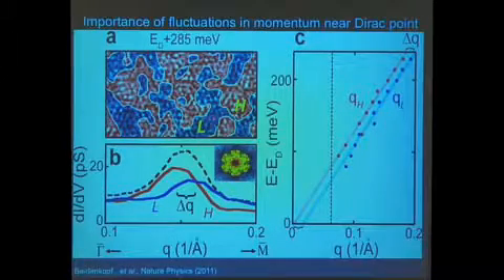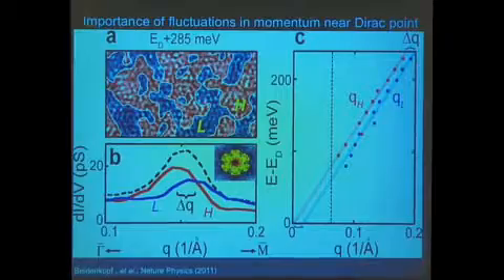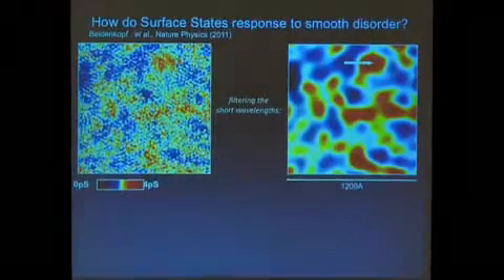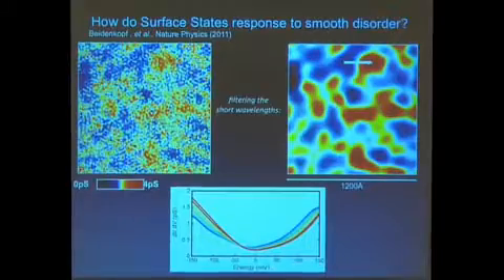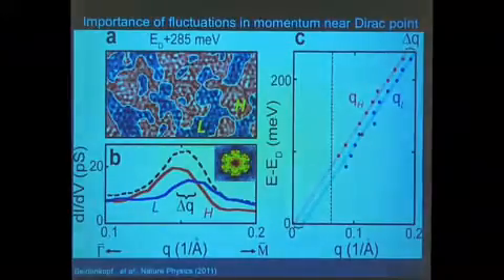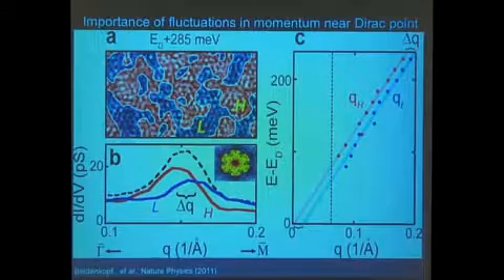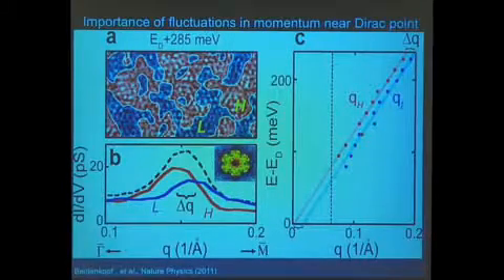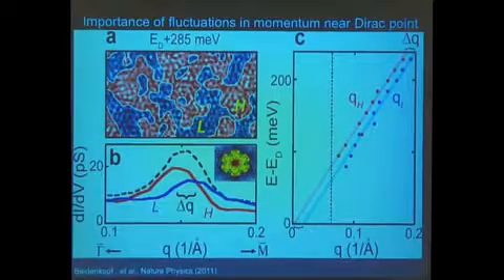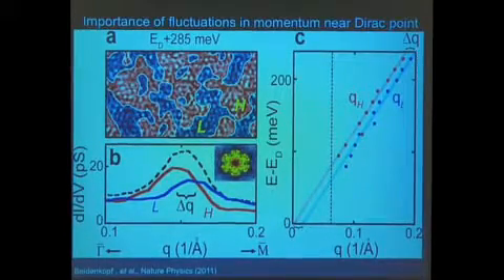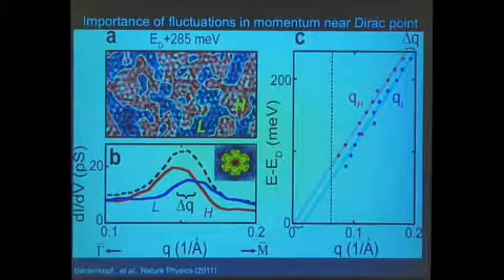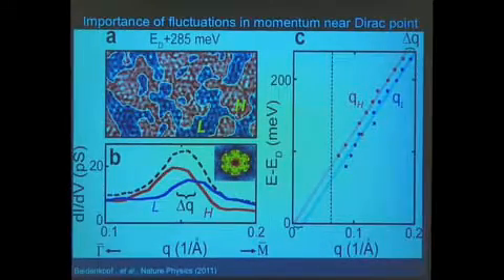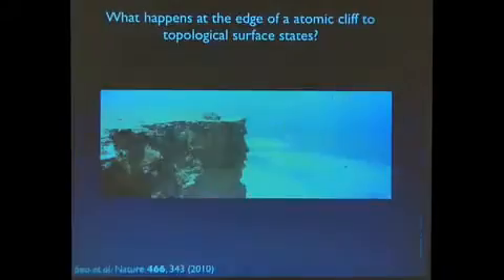No, actually, what happens is that I glossed over this a little too fast. If you break up the sample into different regions corresponding to regions of potential being high or low, you can take a Fourier transform, and you find that the Q vector is actually very different. And as you make the samples cleaner, this distribution of wave vectors becomes sharper and sharper, and the difference between electrons moving in the high potential or the low potential starts to match closer and closer. So this distribution of wave vectors is really associated very nicely with the disorder potential having to do with the dopants in the sample.